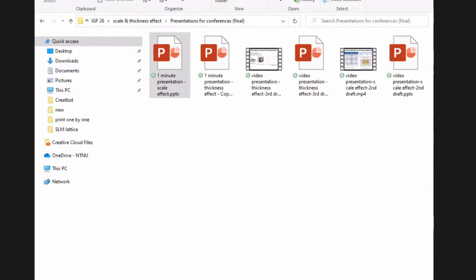For this work, we studied the scale effect on the mechanical behavior of PLA specimens fabricated with FDM technology. The aim of this research is to investigate the influence of the scale of the test specimens on mechanical properties. So in this case, we fabricated three sets of them. The first one is 100% of the scale, which is the standardized specimen, and the others are 50% and 30%. The process parameter is the raster angle, for example, plus minus 45.